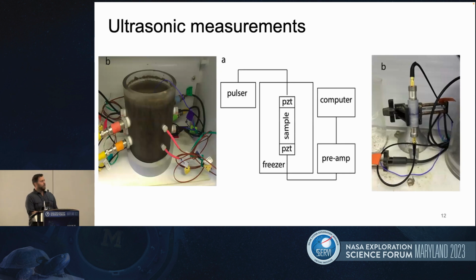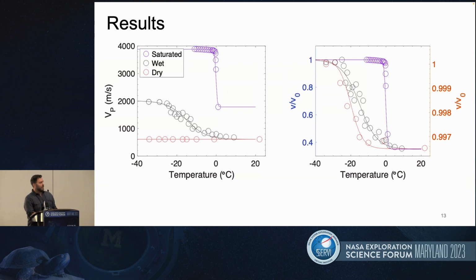And so as a first pass, we've been doing some ultrasonic velocity measurements. We use piezoelectric transducers on two sides of a sample, put it in a freezer, and then we measure wave velocities as the acoustic pulse travels through the material. We've done this on saturated samples, slightly wet samples, meaning equilibrated with atmospheric water, probably with poly-adsorbed layers of water on it, and then oven dried, which means not totally baked off, so maybe monolayer adsorbed materials. And we measure this as a function of temperature.